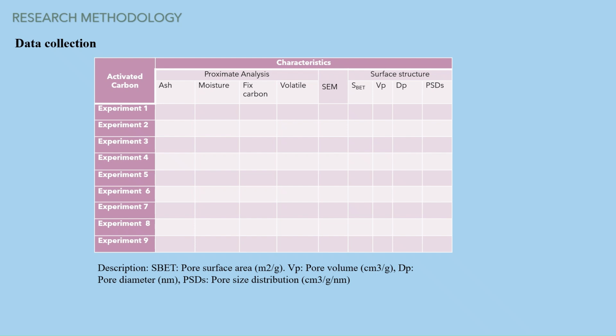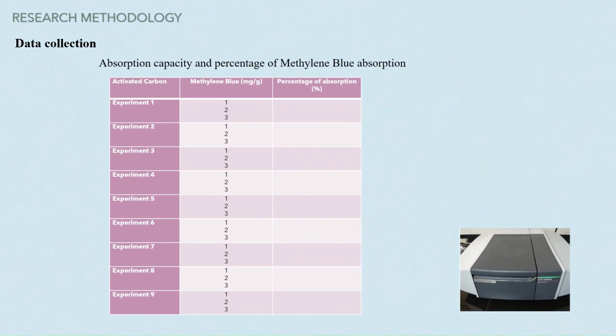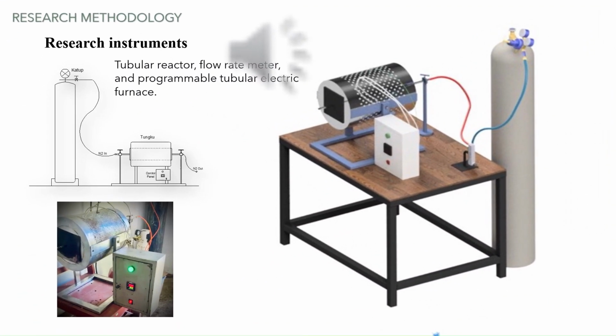Collected data include surface area, pore volume, pore diameter, pore distribution, and methylene blue absorption capacity. At this stage, data on the absorption capacity and percentage of methylene blue adsorption by activated carbon was collected. Each experimental condition was repeated 3 times to obtain representative values. The concentration of methylene blue was analyzed using a UV-Vis spectrophotometer, which was then used to calculate the absorption capacity and percentage. Activation and testing are conducted using a tubular reactor, flow meters, and a programmable electric furnace to ensure stable experimental conditions.